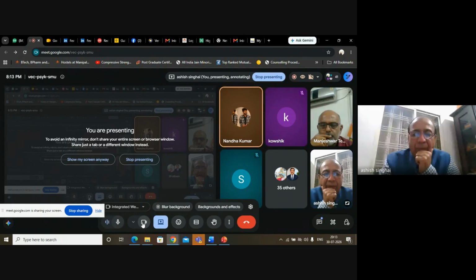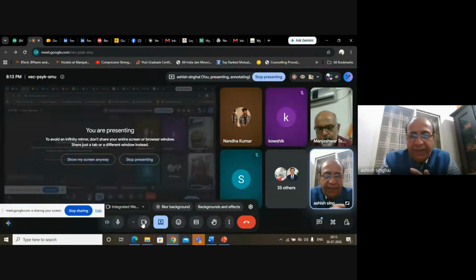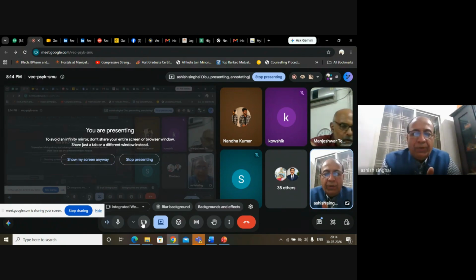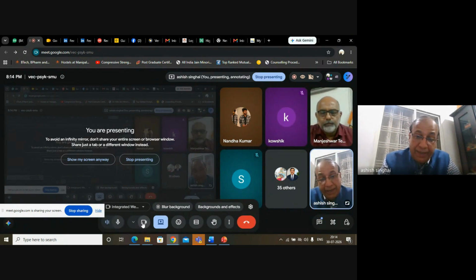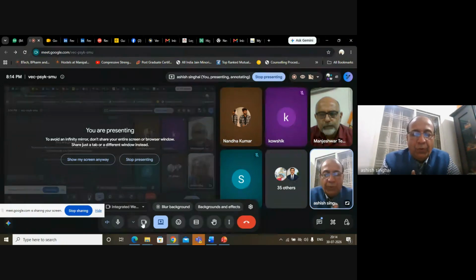No. See, as I said, its setting parameters are determined by the addition of gypsum, which is basically a set retarder. So it does not have any adverse effect as compared to blended cement. I'm comparing it with blended cement at this point in time as far as setting parameters are concerned. So it is almost the same as our blended cements. No difference in setting parameters. IST and FST, that is initial set and final set, are close to similar to blended cements.